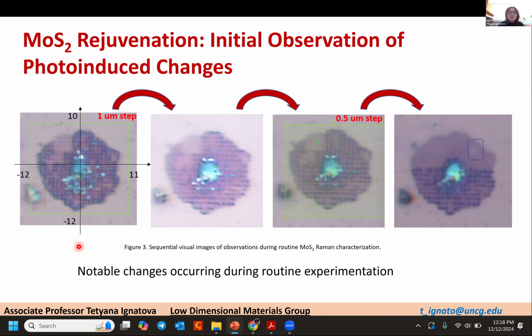The topic of my presentation is molybdenum disulfide rejuvenation. Initial observation of photo-induced changes is presented on this slide. It happened a few years ago when we found that by doing characterization, we had already introduced changes. These ugly pictures were done at an old Raman microscope when a student just took out a freshly grown sample, which was bad, and started doing Raman mapping, and already saw that scanning across causes significant changes in appearance, just optical appearance.